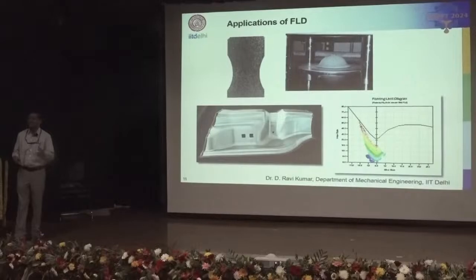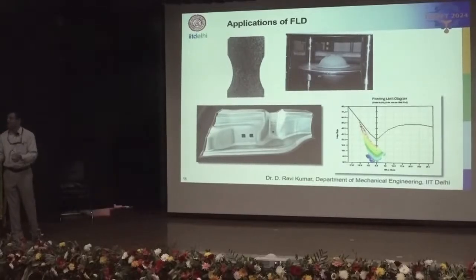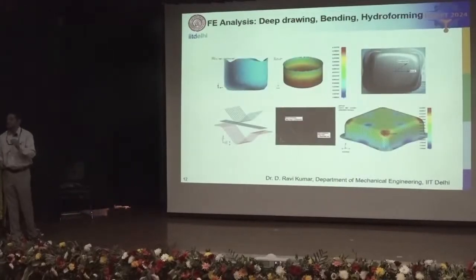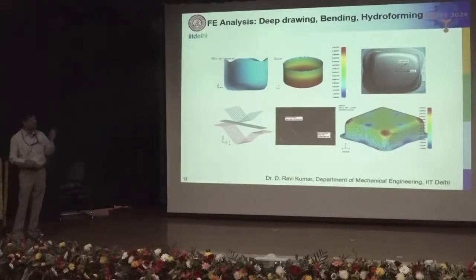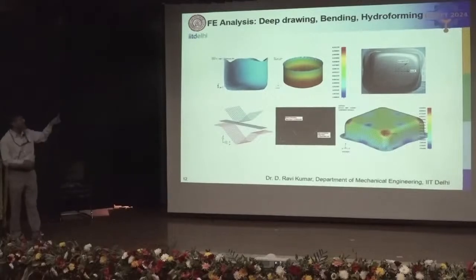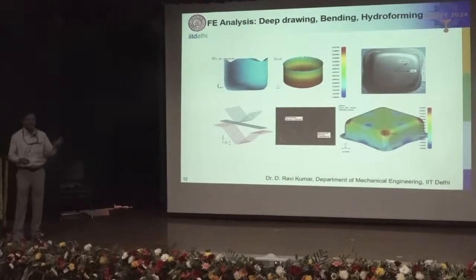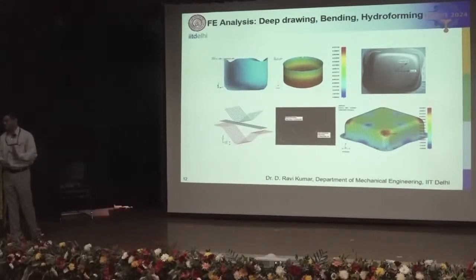But often in the industry, we have components with very complex shapes, and we quickly need the strains on the formed component. So what do we do? We use finite element analysis or simulations to quickly predict the strain distributions, stress distributions, and so on. So in the finite element simulations, to predict whether failure takes place or not, the experimentally determined forming limit curve can be used. Even though it has its own limitations, it still serves as a general failure criterion for quick visualization of the success of the forming operation. Okay, and if we don't have the experimentally determined forming limit curves, they can also be predicted using some analytical relations. So that is also possible.